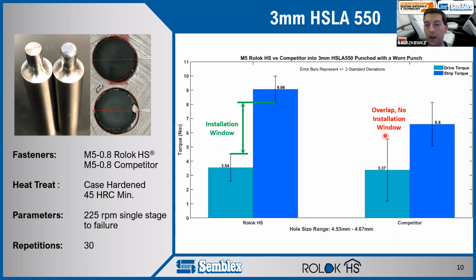torque. But in order to account for variability, we typically add 3 standard deviations on the mean, and that's what these error bars represent. So our upper drive torque limit is basically right up here on the top of this error bar. Our lower failure torque limit is at the bottom. We want there to be a gap between these.